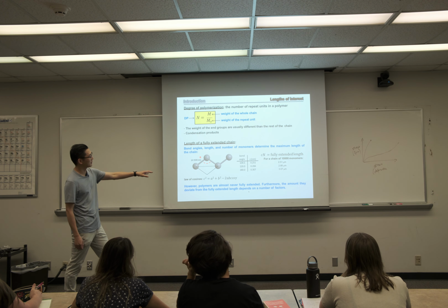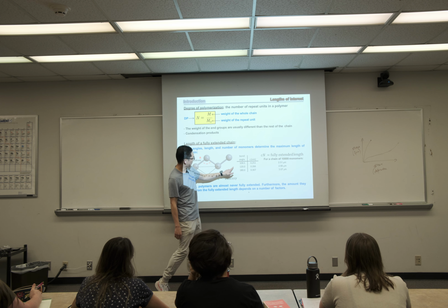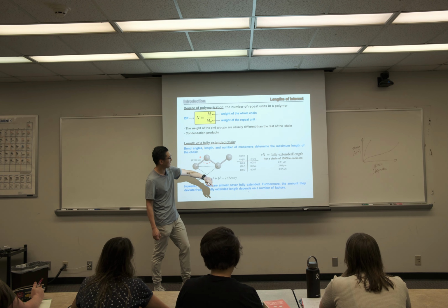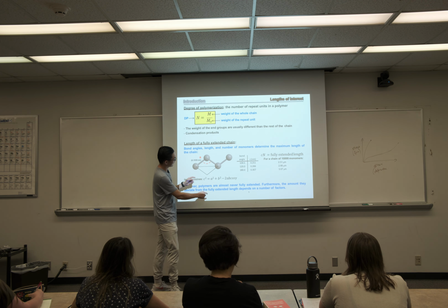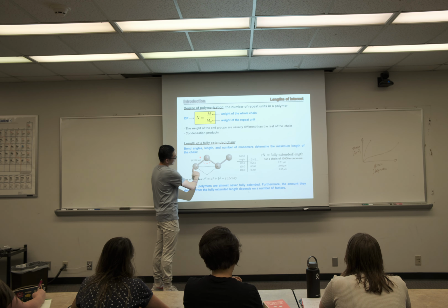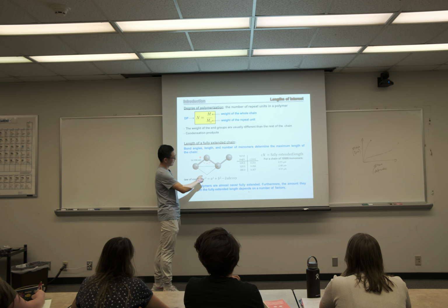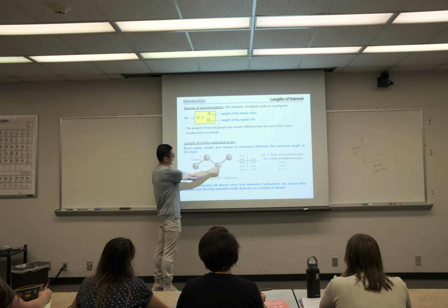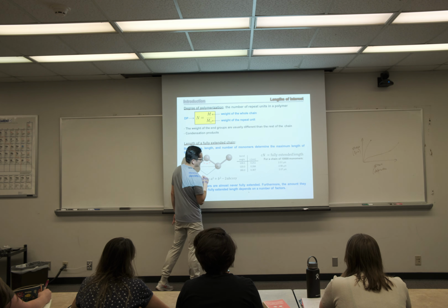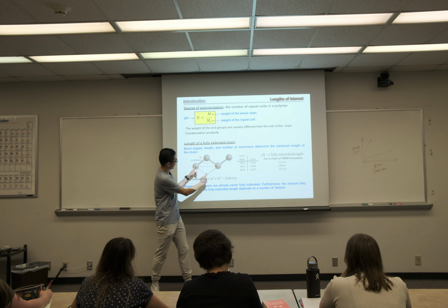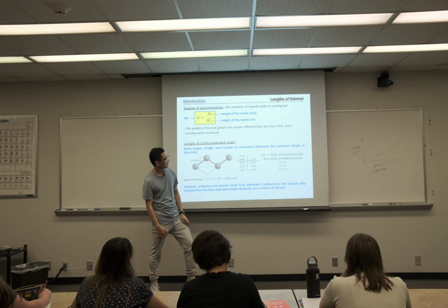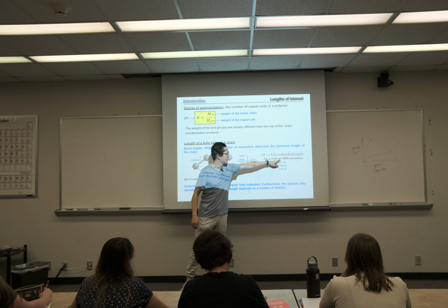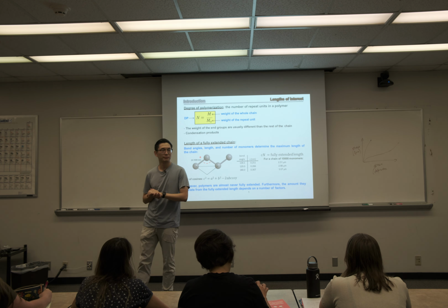Then you can use repeat. If it's 180 degrees, you're gonna have a perfect straight line. C here just defines the angle between this dashed line, nothing fancy. If you know A and you know the angle, you can calculate C. If it's 180, that just happens to be a perfect straight line, so C will be twice the length. If you change the angle, your C is gonna be smaller, and you can calculate the fully extended chain for 10,000 monomers.